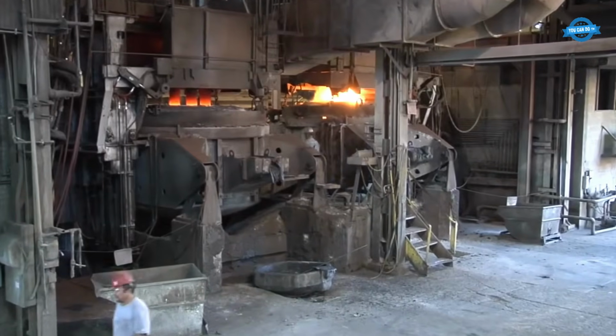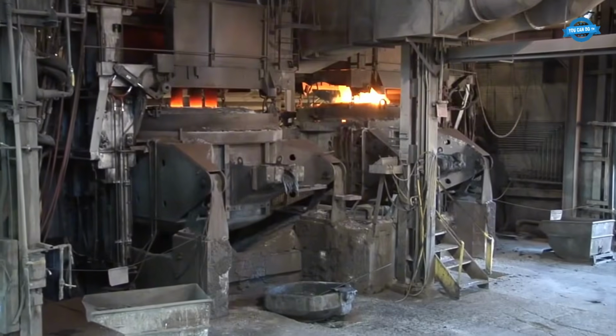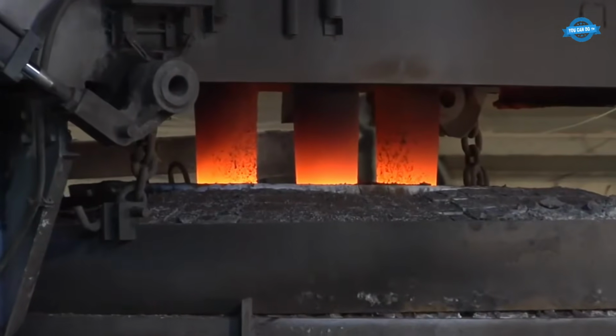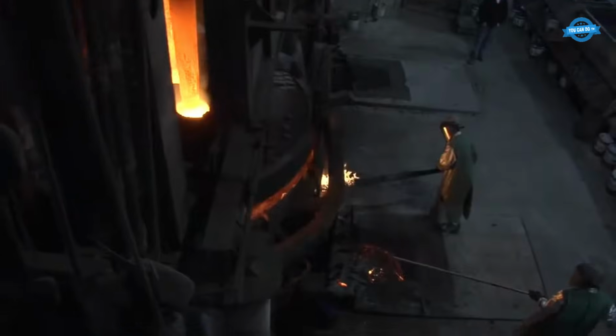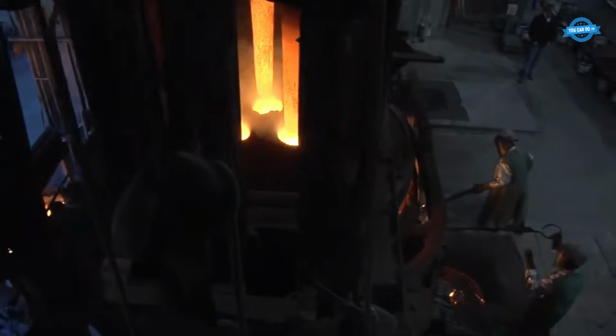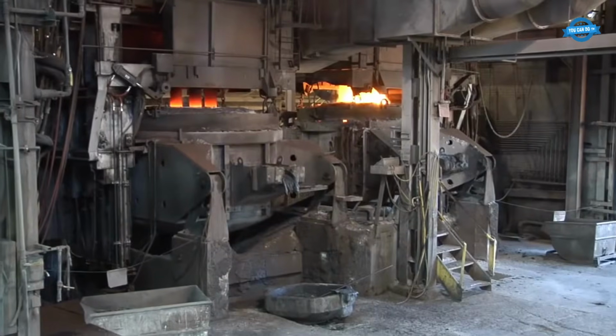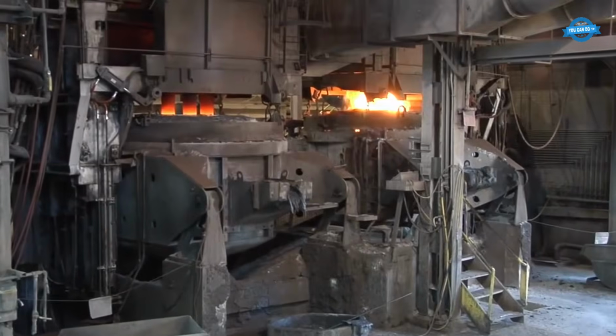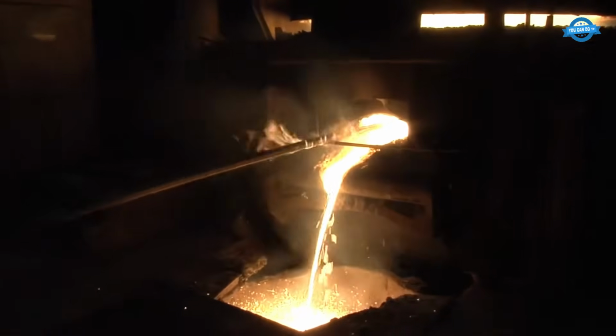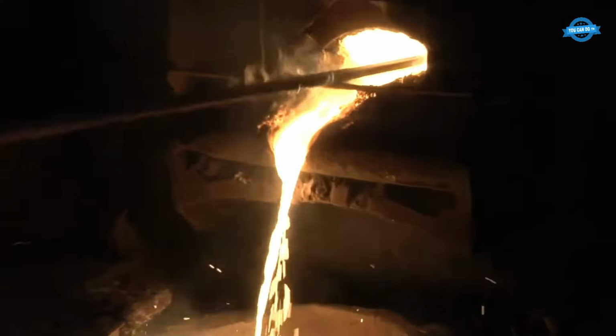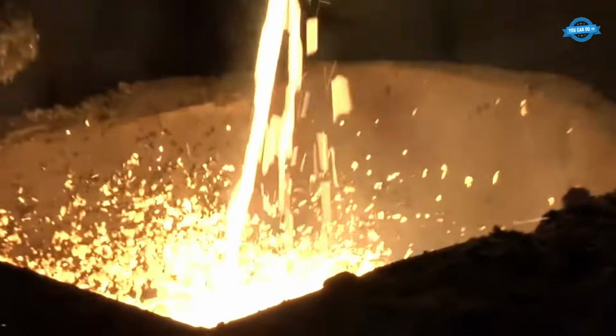The heart of a steel foundry is an electric arc furnace. And the first time you understand what it actually does, it's hard to believe this technology exists at commercial scale. 3 furnaces charge 10 to 11 tons per heat, with a maximum around 24,800 pounds and a typical cycle of 2.5 hours.